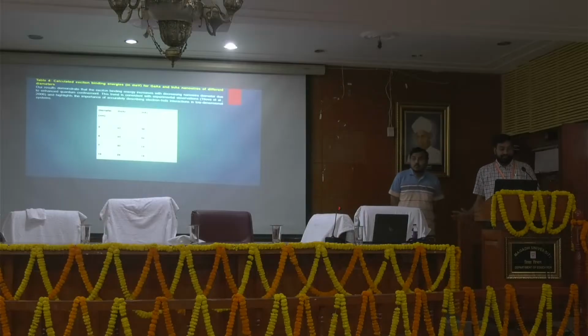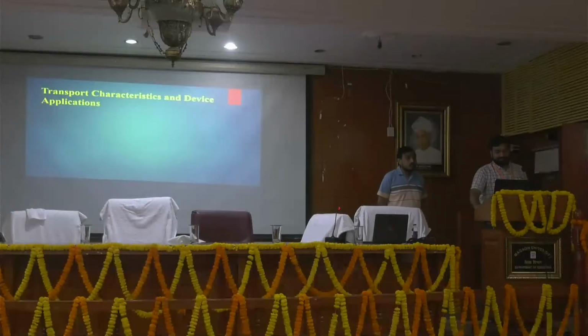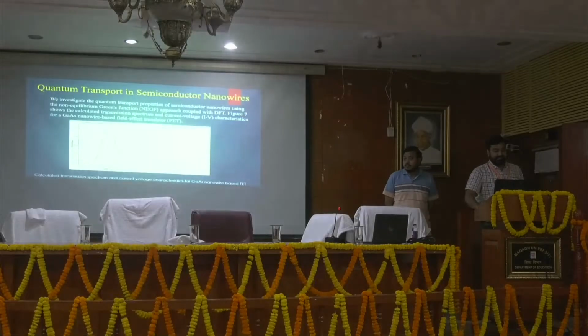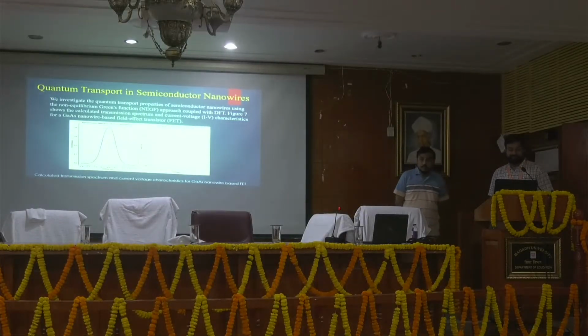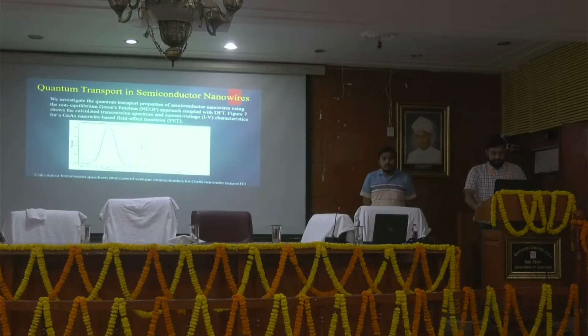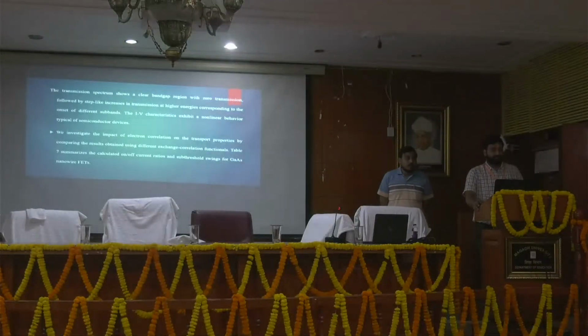Now the data for calculated exciton binding energy in milli electron volt for gallium arsenide and indium arsenide nanowire of different diameters. According to diameter, binding energies are mentioned for 3 nanometer, 5 nanometer, 7 and 10. Transport characteristics and device application. Quantum transport in semiconductor nanowires looks like this, which is using non-equilibrium Green's function.